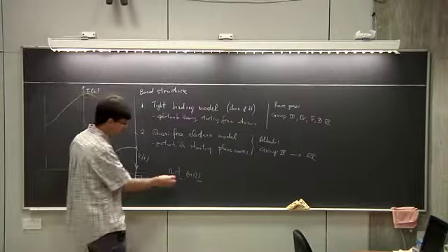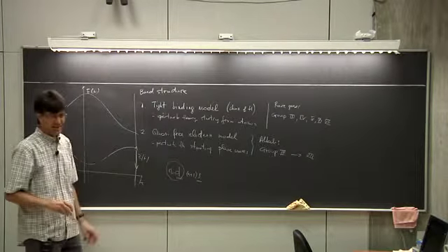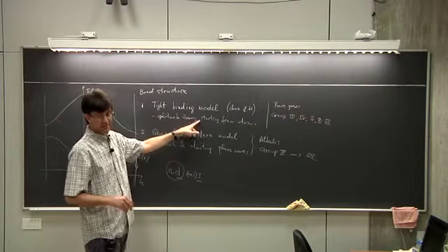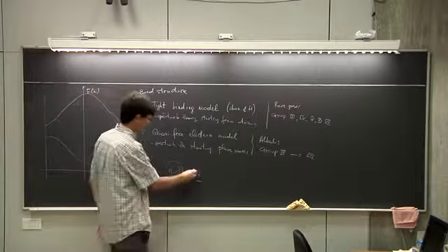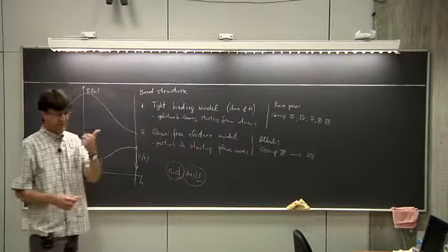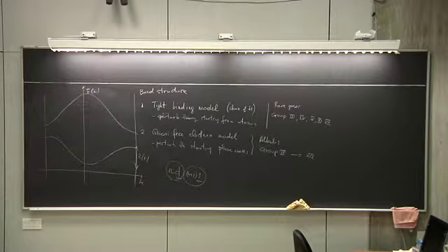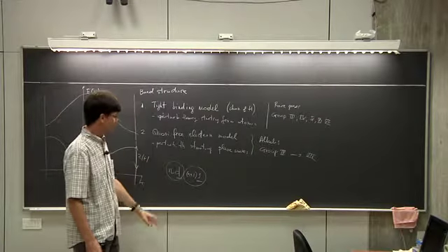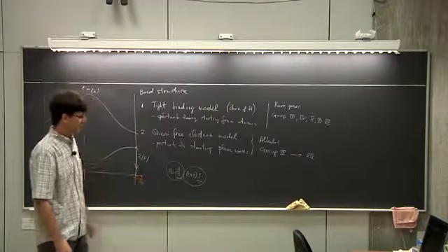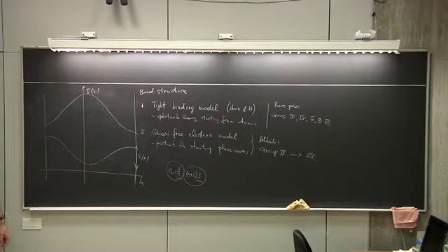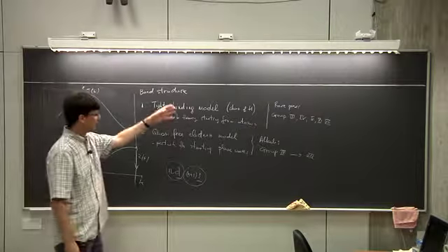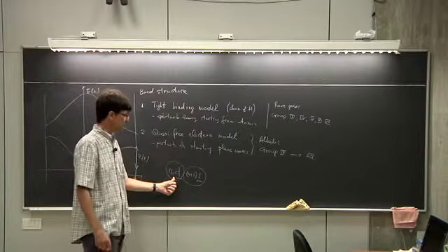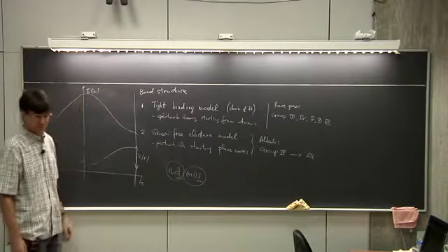The next one will be 5d 6s. Now, d orbitals tend to be very localized, so d orbitals are typically described quite well by the tight binding model. S orbitals, unfortunately, behave like the s orbitals of the alkali atoms, so they're very delocalized. So transition metals are a somewhat tricky system because different categories of orbitals behave in a different way. None of the two approximations works for both, and in principle you should be using the tight binding to describe the d orbitals and the free electron model to describe the s orbitals.